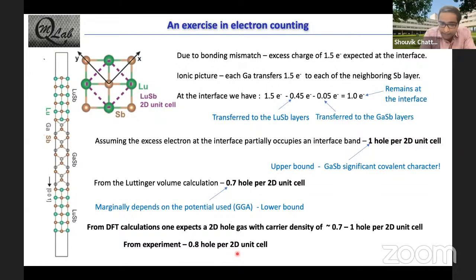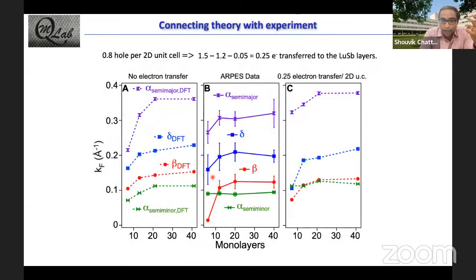Now, if we really understand what is happening in our system, we can back calculate that if we have 0.8 holes per 2D unit cell, what we expect is that there are 1.2 electrons at the interface. There is 0.05 that goes to the gallium antimonide. So the actual number of electrons transferred to the lutetium antimony is about 0.25. Now we can add this 0.25 electrons to our original bulk slab calculations and again recalculate how we expect the Fermi wave vector of the electron pocket to change as a function of layer thickness. And now we really find a very good correspondence between the experiment and the theory.